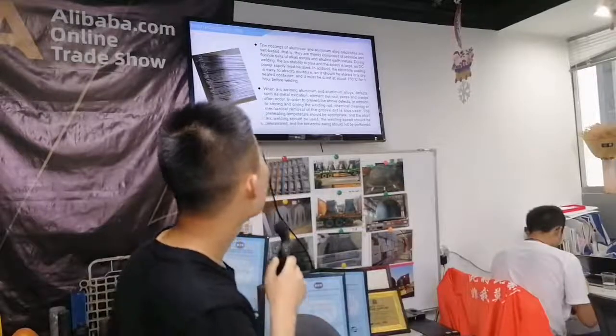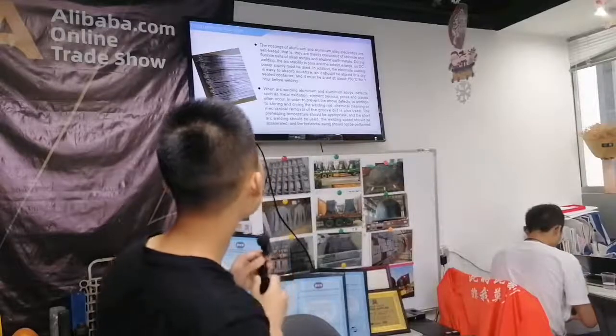The coating of aluminum and aluminum alloy electrodes is salt-based. That is, they are mainly composed of chloride and fluoride salts of alkali metals and alkaline earth metals. During welding, the arc stability is poor and the splash is large, so DC power supply must be used.